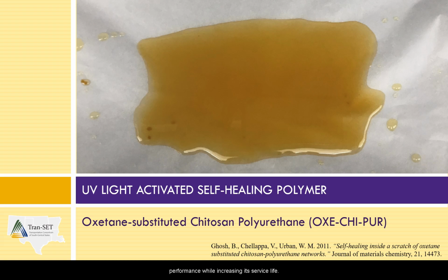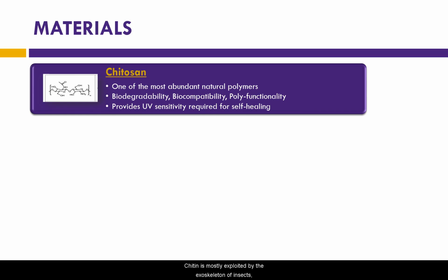The UV light activated self-healing polymer is constructed using three main materials. The first material is called chitosan, which is an important derivative of chitin. Chitin is a natural polysaccharide and is one of the most significant biopolymers in today's world. It is also considered the second most abundant polymer. Chitin is mostly extracted from the exoskeleton of insects, shrimp, and crabs. Chitosan is biodegradable, biocompatible, and non-toxic. Chitosan was selected for the self-healing polymer to provide UV light sensitivity.